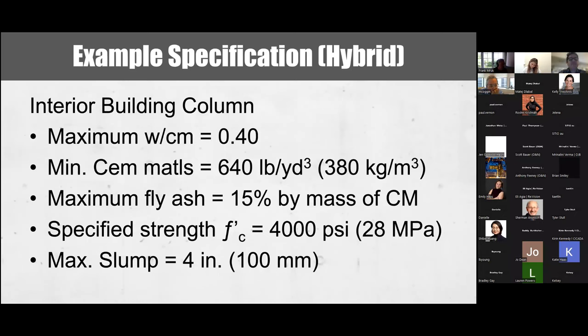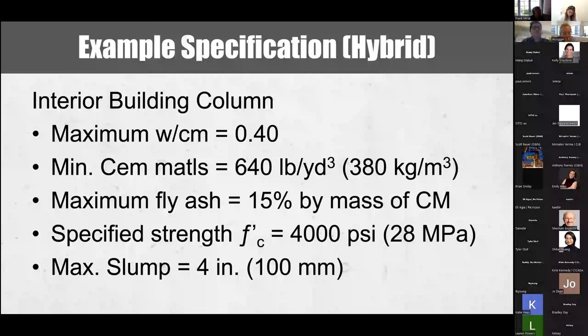Since the column is protected from exposure, the water to cement ratio limit is not necessary for durability, and the requirement for a minimum cementitious content is not needed to meet the strength requirements. Presumably, the limit on fly ash is to ensure rapid strength gain for form stripping, but this is an issue of means and methods of construction and should therefore be avoided in the specification.